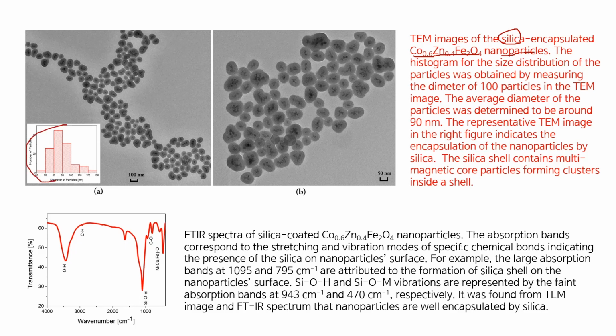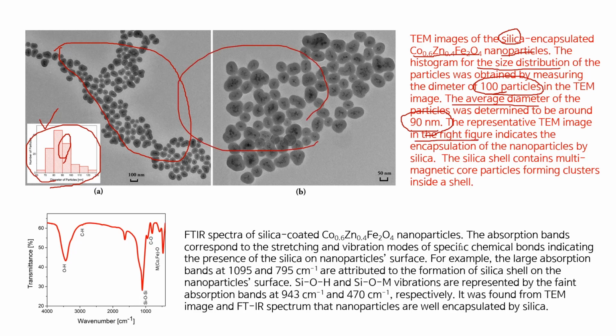The histogram here for the size distribution of the particles was obtained by measuring the diameter of 100 nanoparticles in the TEM image. So we collected 100 nanoparticles and measured the diameter of the particles. So this histogram shows the particle size distribution. The average diameter of the particles was determined to be about 90 nanometer. The representative TEM image in the right figure indicates the encapsulation of nanoparticles by silica.